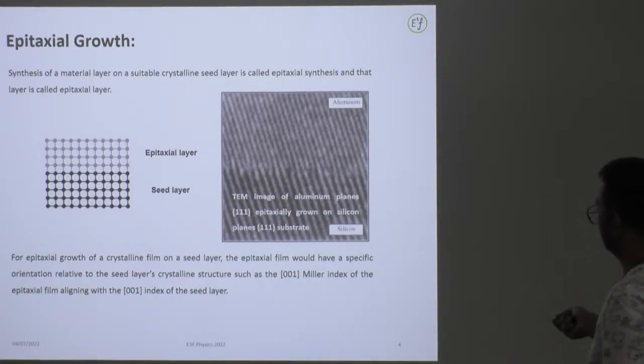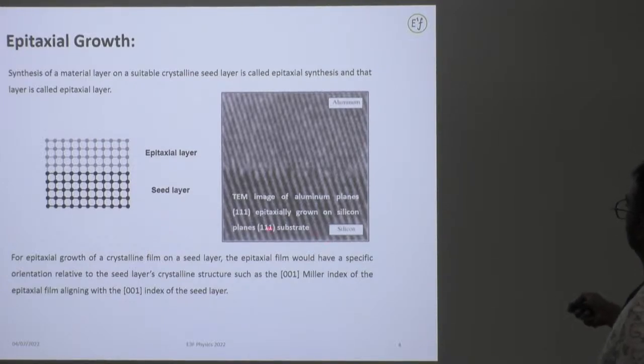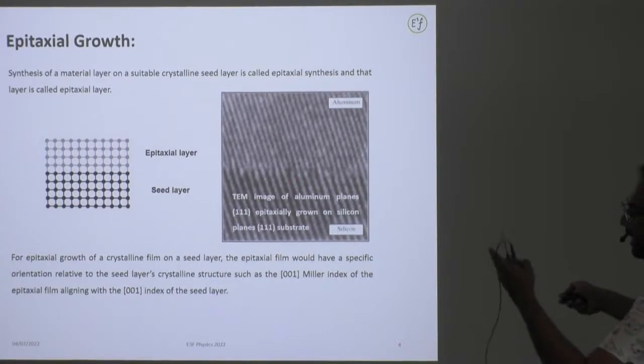So here is an example. Silicon is on the bottom part and aluminum is on the top. So this is a TEM image, transmission electron microscopy. You can also search about that. That is a separate thing. But this is an image on atomic scale. The scale should be here. It's just 5 nanometers. So this is quite a good characterization technique. I would say that you can check atomic layers, and each individual line is showing atomic layers.